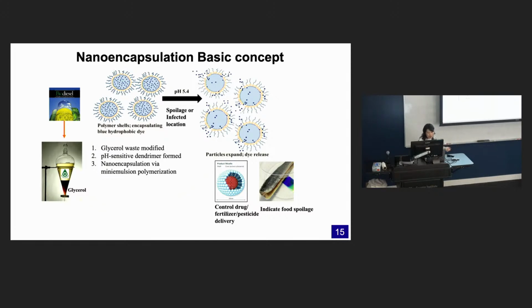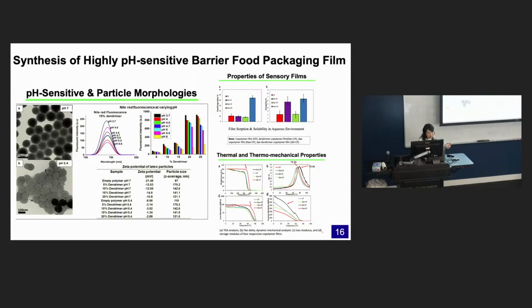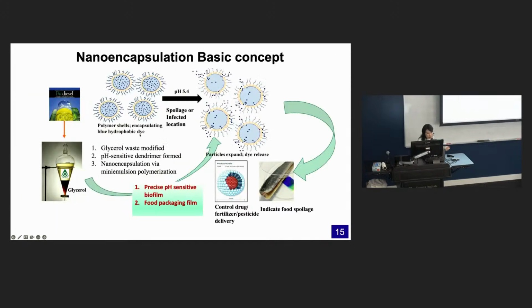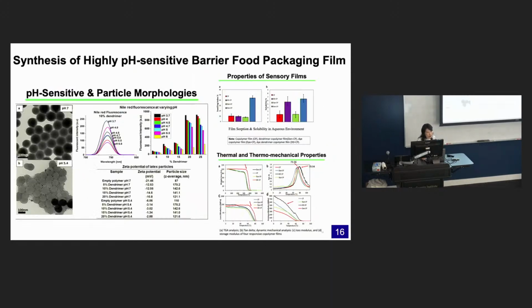And also, we mentioned that we want to get this precise pH-sensitive biofilm. So we can adjust our nanoshell structure. So then we can control the dye release rate. So then we can detect the pH sensitivity. So here is showing our results. From here, you can see pH 7.